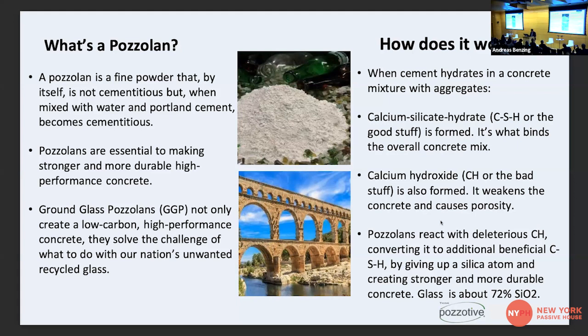And basically how it works is just like any other pozzolan. During the calcium silicate hydrate reaction, two products are formed. One is calcium silicate hydrate. That's the bonding agent that bonds the aggregates together. And the second is calcium hydroxide, which actually creates porosity in the concrete, which is deleterious to concrete.